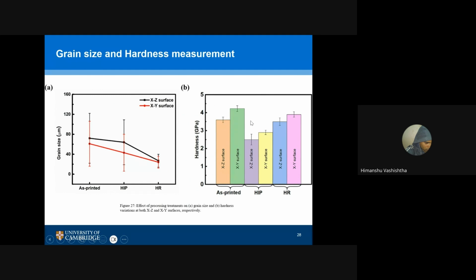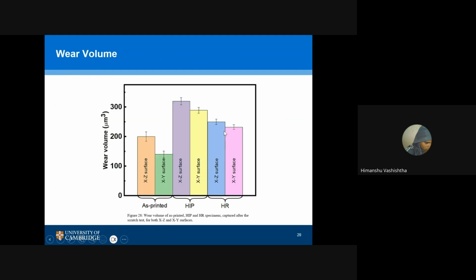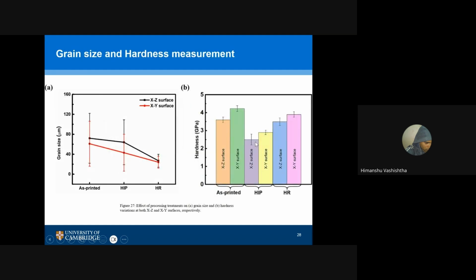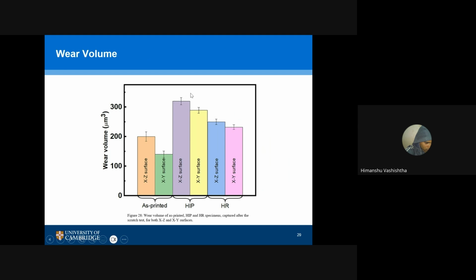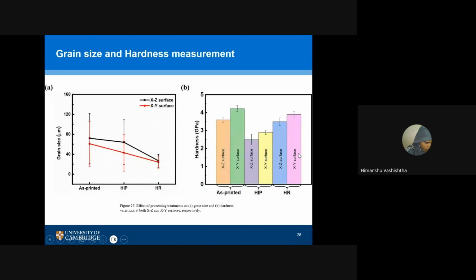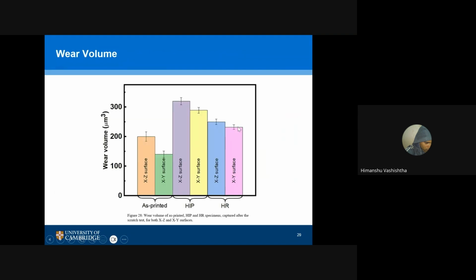The highest hardness was for the as-printed case, and that's why it's showing the lowest wear volume. Similarly, the hardness was the lowest for the hot isostatic pressing process, and here when the hardness was lowest, the wear volume is the highest. And when the hardness is in a moderate range, it's approaching the highest one, but not quite, so the wear volume is this much.